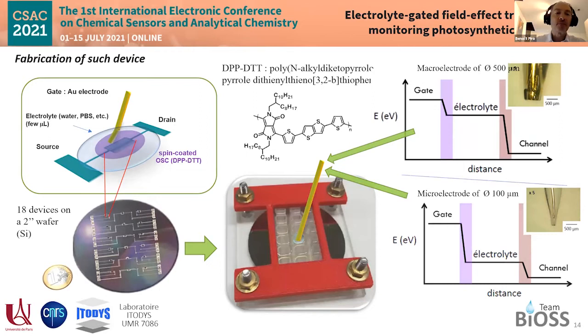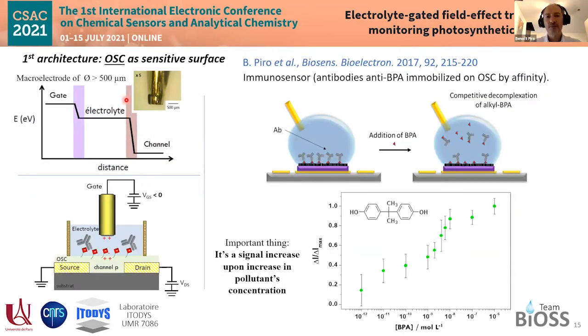If we use large gate electrodes, say macroelectrodes as gate, we could use naturally the electrolyte channel interface and functionalize that interface, say with antibodies, antigens, DNA, or whatever, to sense a binding typically. This is an example, but again, I will not take too much time on this because I would like to switch to another application. But it's possible, and it has been well described now, to functionalize the channel interface to sense some tiny changes at the interface with the electrolyte with these devices, and amplify the change into a current, of course.